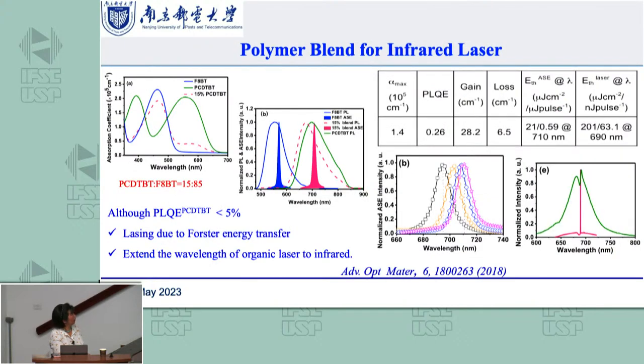A similar work we did is to use a PCDTBT blend with F8BT. You know the PCDTBT is a solar cell material, almost no light comes out. The quantum efficiency is less than 5%. But once you blend that as a guest into the host material F8BT, we are able to achieve the laser from this system. So that means as a laser material, it doesn't have to be a very good LED material. You see this one, PCDTBT, almost no light comes out, but if you choose a good system, you can make it a laser.